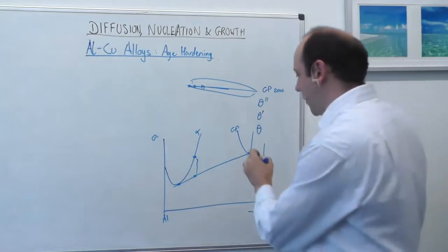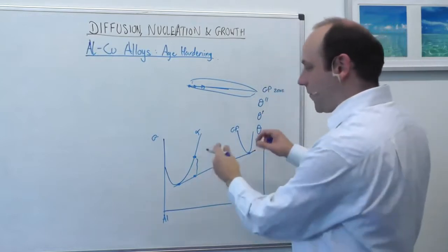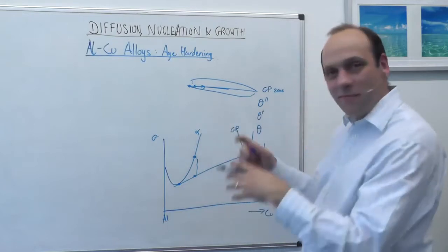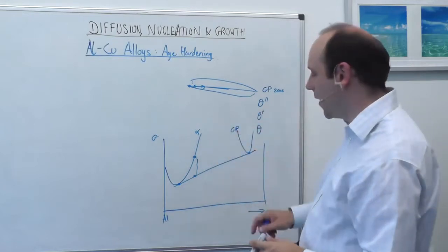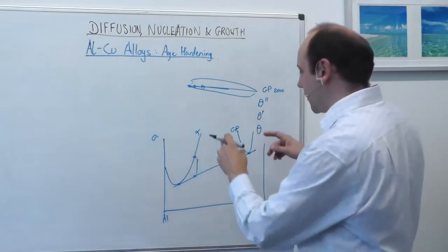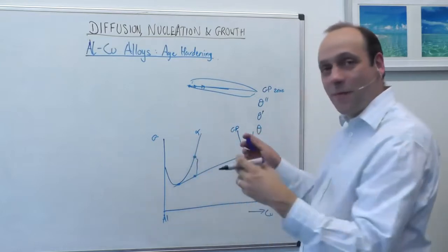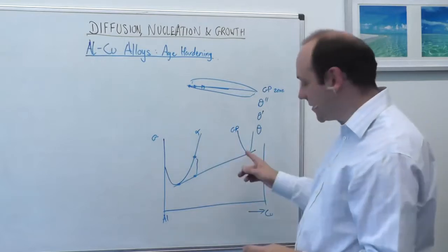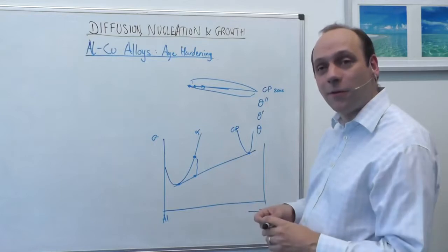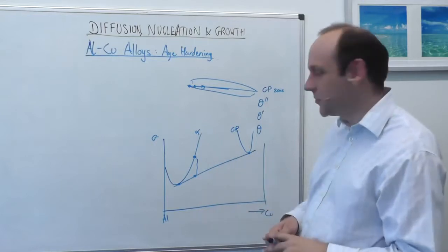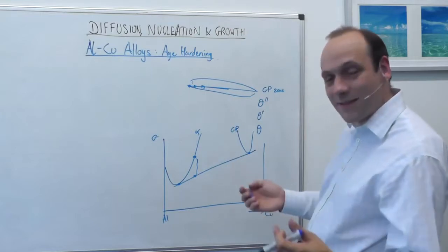And then what can happen, and this is quite favourable, this doesn't require a lot of surface energy for the GP zone, it's only 2 atoms thick, and it has the same sort of crystal structure as the alpha. So this doesn't have a very big sigma, a very big surface energy that penalises nucleation. So this happens at very low undercoolings, and can happen off of small little lattice defects, interstitials or whatever, vacancies.